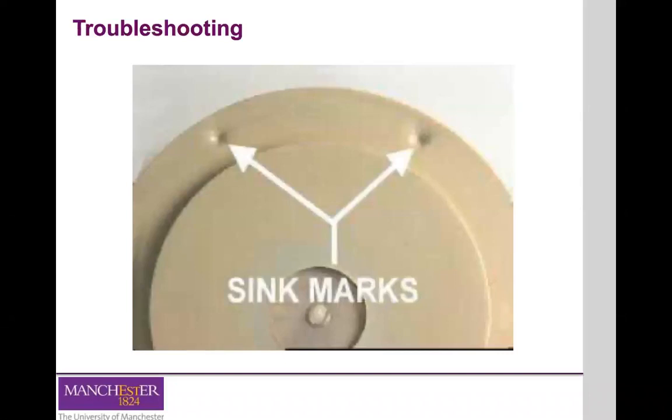So one very common defect in injection molding is called sink marks. Sink marks, as you can see in this picture, can generally be defined as a depression resembling a dimple or a groove. And this is normally caused by excessive localized shrinkage of the material after the part has been cooled. Depressions such as these usually form over the thicker sections of the parts, or hot spots, if you prefer. And this is due largely to the difference in cooling between the thick and the thin sections. And this differential cooling will generate stresses that, as we've seen, and similar to metal casting, will then cause these depressions by simply pulling the material and the surface towards the center.